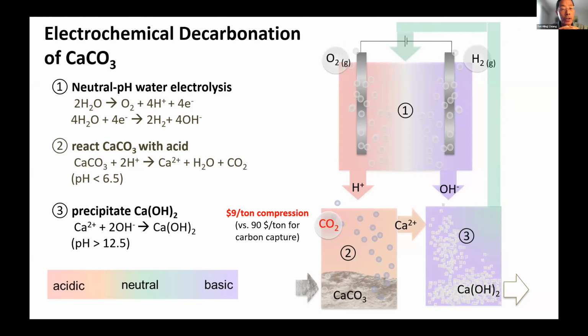And virtually all metal carbonates in acid will decompose and release CO2. And it'll do so at ambient temperature. This is the vinegar and baking soda trick. Right? And so that produces pure cold CO2, which you could capture. It's already captured, rather, which you could sequester more easily than hot flue gas CO2.